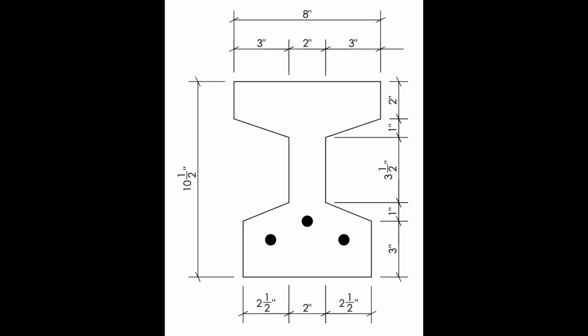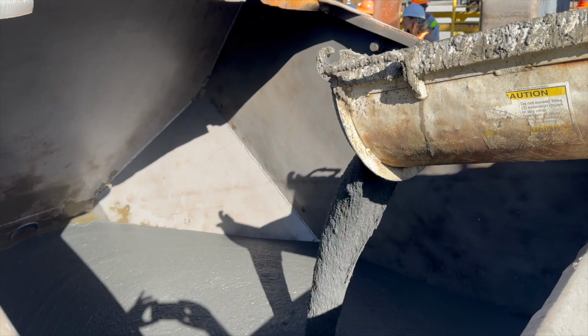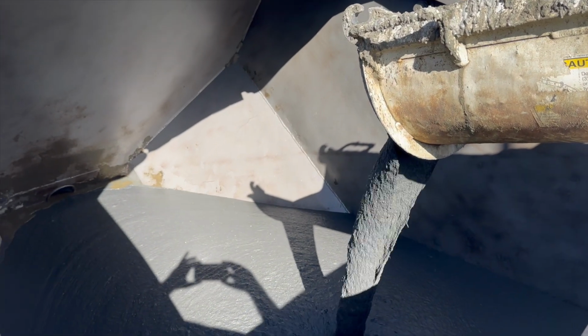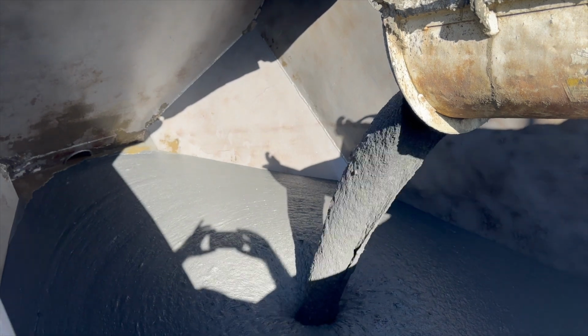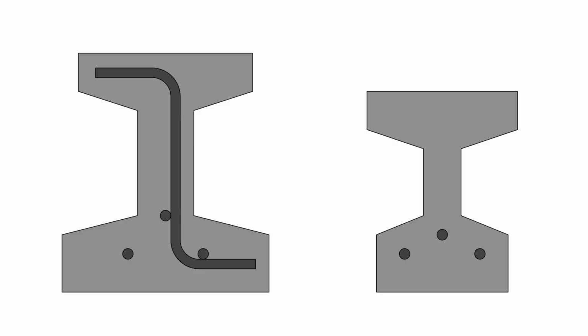This is what our design looks like. The beam is only 10.5 inches tall and is 8 inches wide at the top and 7 inches wide at the bottom. The beam uses 3 9/16 pre-stressing strands in a triangular pattern and actually no shear reinforcement. This is important because we want to minimize the amount of mild steel in this beam so that we don't get any disruption of the flow of the fibers.